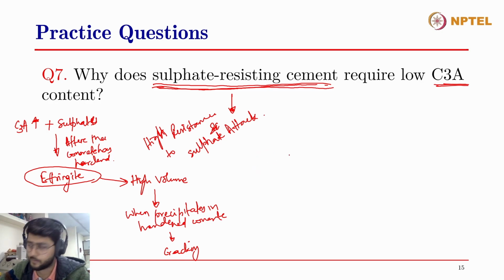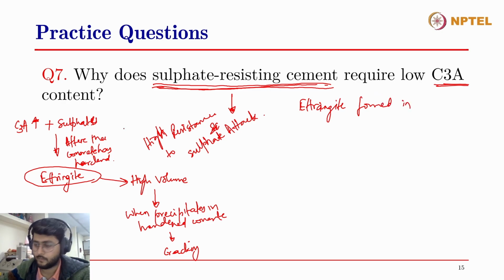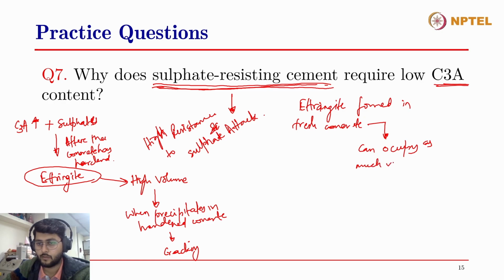So we want ettringite to be formed in the system, but when the concrete is still flowable, in a plastic state. Ettringite formed in fresh concrete can occupy as much volume as required, because the concrete is in a plastic state, so there is high porosity, a high amount of voids, and the concrete can readjust itself to the volume taken by the ettringite.